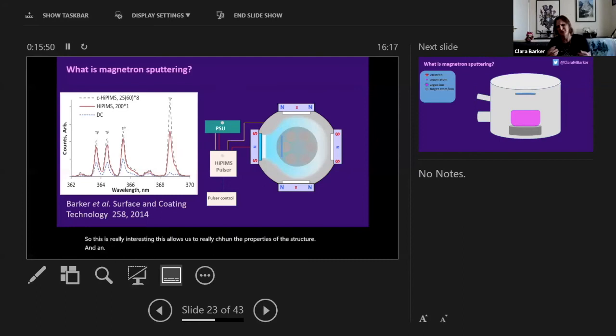I said before that we can't see the individual atoms or ions in the plasma, but what we can do is measure the wavelengths that are there in the chamber, and we can figure out that this one's a titanium atom peak, this one's a titanium ion peak, and this one's an argon ion peak. So we can figure out what species we've got in the system.